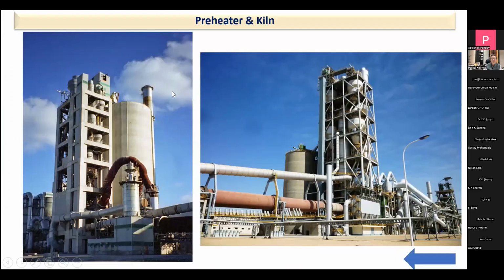After the wet process, the dry process kilns came into being, and they came with the preheater along with the calciner. Now this preheater is typically more than 150 meters, that is nearly a 50-story structure. Earlier it started with a 4-stage preheater, then it went on to a 5-stage preheater, and now we are using a 6-stage preheater. By increasing the stages, we are basically doing better heat recovery.